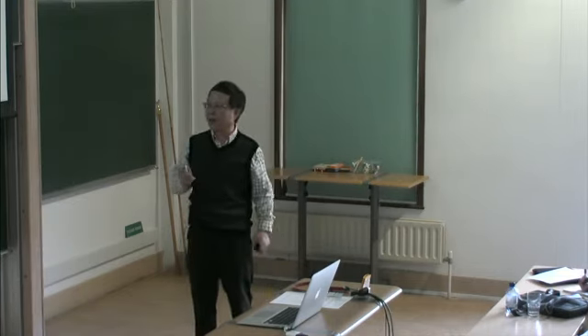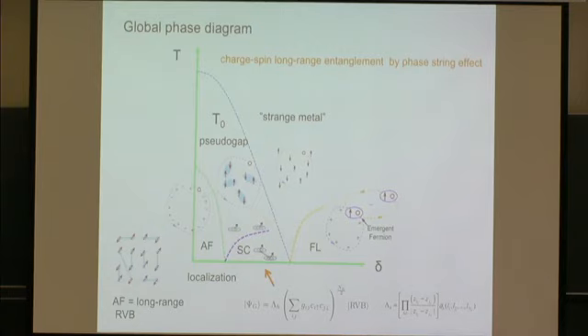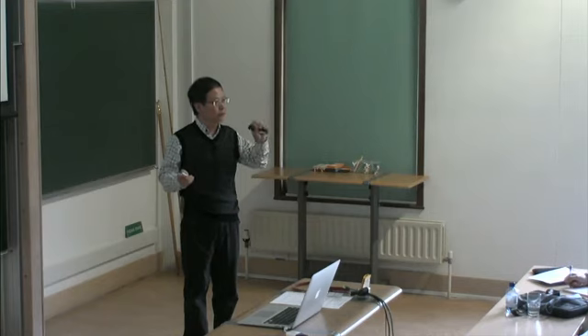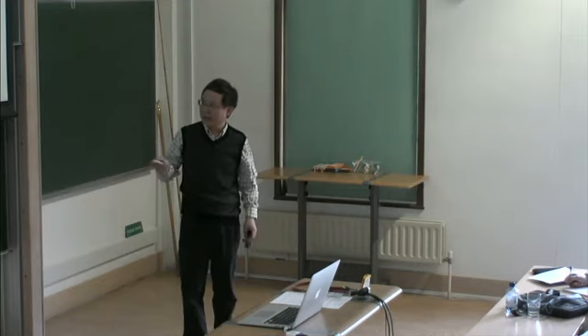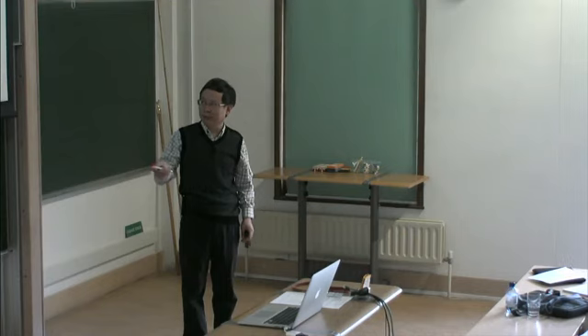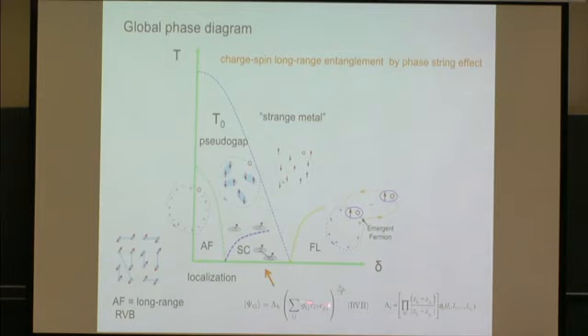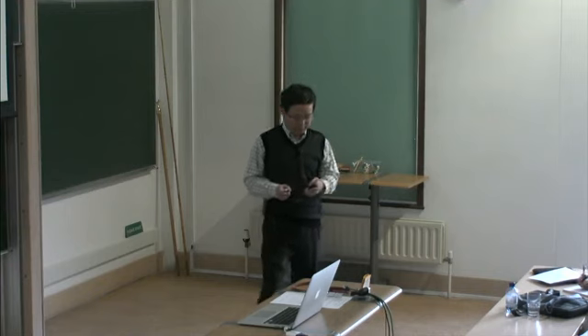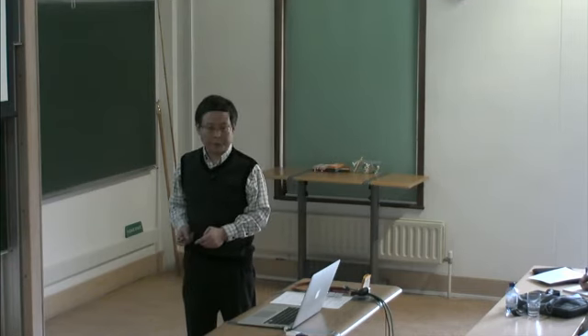And there's a simple wave function that can describe it. The most important thing in this wave function is that you have this simple Jastrow type factor which keeps track of the sign structure. So it's no longer the fermion sign. This is something new. And the rest of it is just the antiferromagnetic background, which turns into a short-range antiferromagnet. Then by putting holes there, by taking electrons out in pairs, you have some kind of order parameter which can be smoothly described in this new formulation.